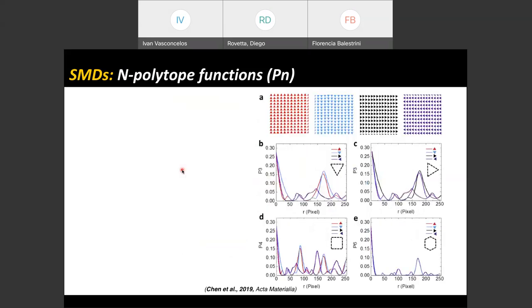Let's look here at a synthetic example. What you see here is four materials that have the same volume fraction, right? So imagine these triangles are pores, triangular pores, oriented in different directions, as you can see with the colors. The porosity or volume fraction is fixed. In fact, when you look at these probability curves, the value at the origin is always volume fraction or porosity. So you can see they all have the same. But if we look at the polytope, so B, C, D, and E are each the curves from different polytopes for each one of the materials, you can compare the color of the curves to the color of the materials here. So you can see which is which.